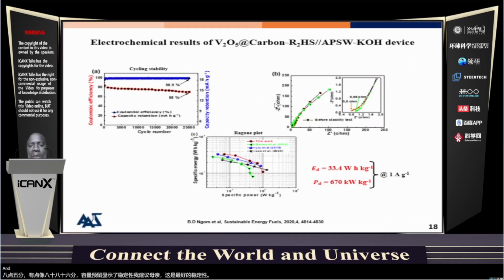And finally, we measured the energy density of 33.4 watt-hour per kilogram, as well as a power density of 670 kilowatt per kilogram, which is showing the potential that these electrodes, which are derived from hibiscus sabdariffa, could be used in supercapacitor devices as an electrode material.